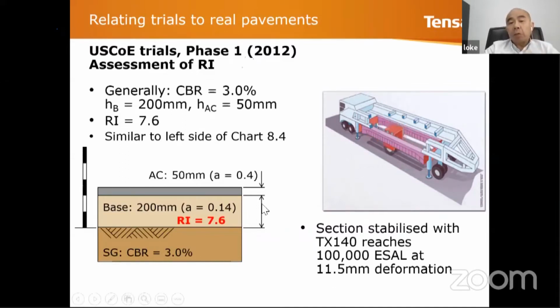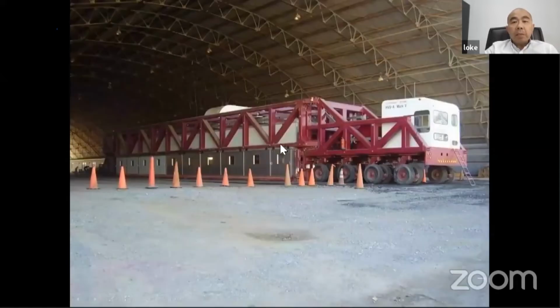is very small. So in the test, we placed 50 millimeters of asphalt concrete, which is basically asphalt. And then you have 200 millimeters of base course. The CBR of the soil is about 3%, which is about 75 kPa undrained shear strength. And this is the big truck.